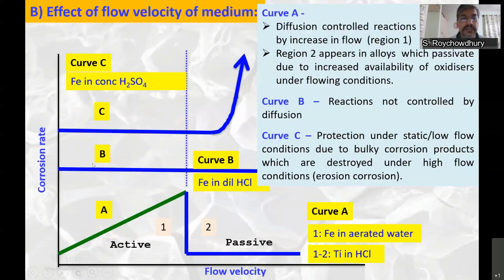Second possibility is B. So there is little or no effect of flow, like in curve B. These reactions are not controlled by diffusion, like iron in dilute acid. It will keep on corroding irrespective of the flow velocity.